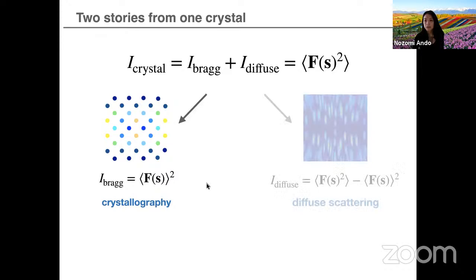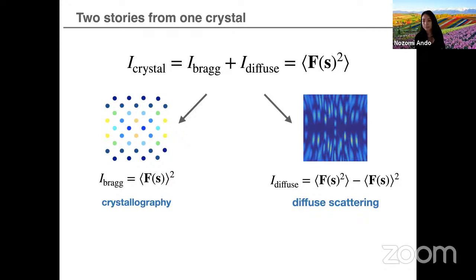It's a continuous function. And why do we care about diffuse scattering? That has to do with the fact that with crystallography, we get information about the average. So the average structure factor is a function of the average electron density in the unit cell. And we can get information about atomic motions in terms of just the displacements, the B factors, but it doesn't tell us whether those displacements are happening in a correlated fashion. That information only resides in the diffuse scattering signal.